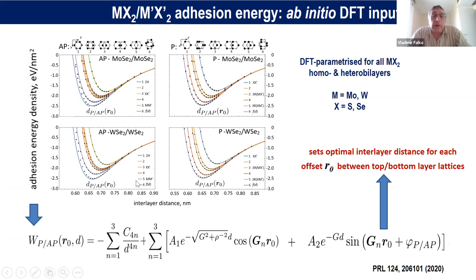So what you see in these panels, on the left-hand side, is analysis of bilayers with anti-parallel stacking of the unit cells, and not a surprise that the lowest energy configuration comes as 2H stacking, which is what grows in the bulk material. The next one on the energy scale is the stacking where you put metal on top of metal in the two layers, but now the chalcogens are not on top of each other. The chalcogens, because of the antiparallel orientation of the unit cells, are actually at the largest distance from each other. And actually the distance between chalcogens, when it is the largest, determines the energetics of the interlayer interaction, because the chalcogens are in the outer sublayers of the crystal, and also they have p orbitals which are sticking out, which provide the interlayer interaction repelling from each other, and therefore the largest distance between chalcogens is what the crystal wants to have to minimize its energy.